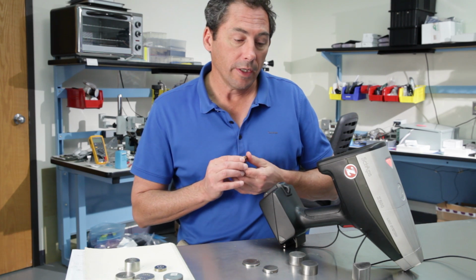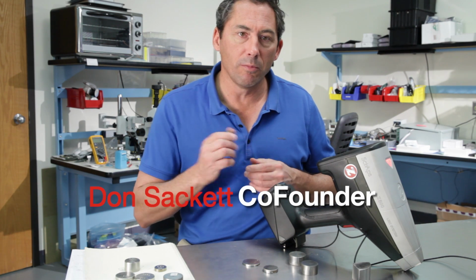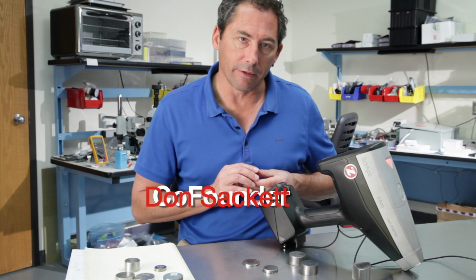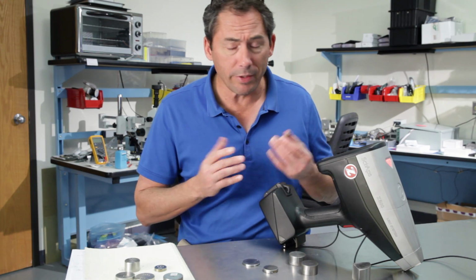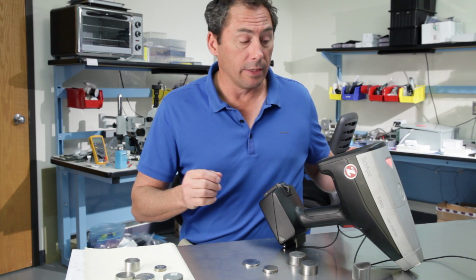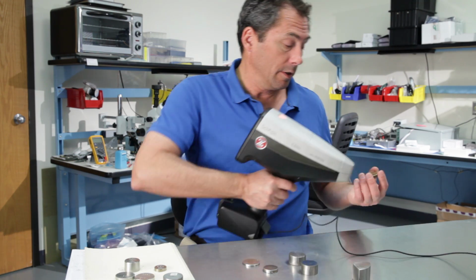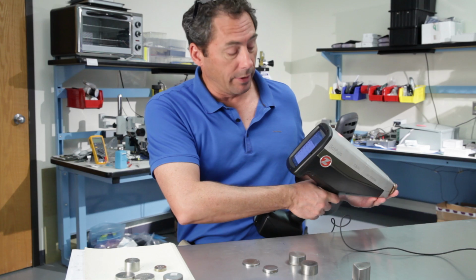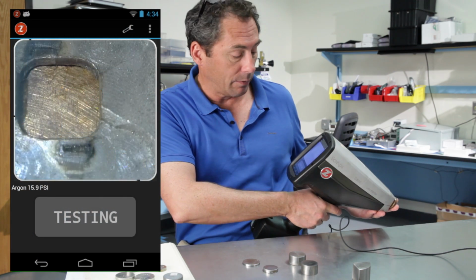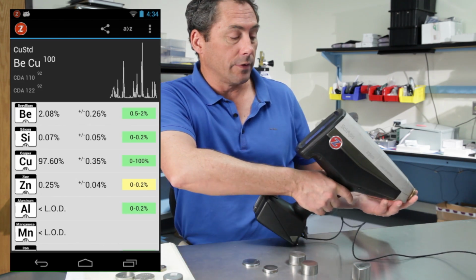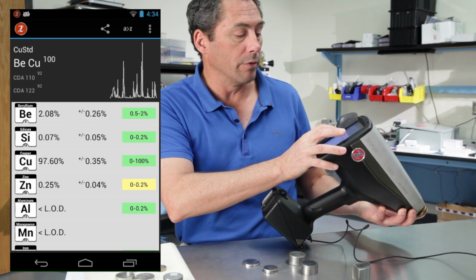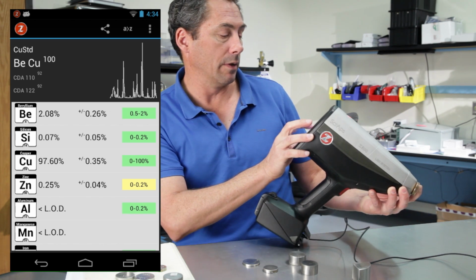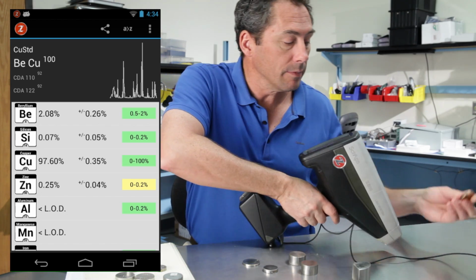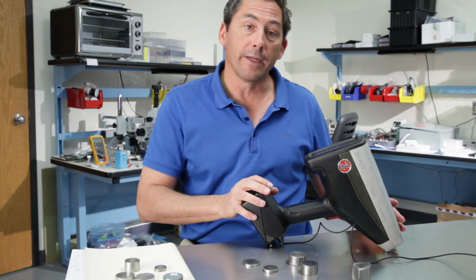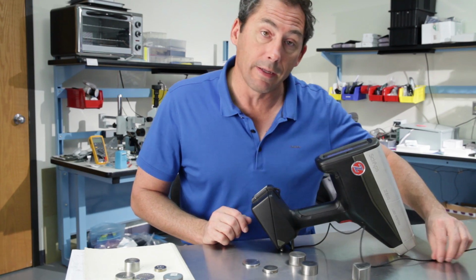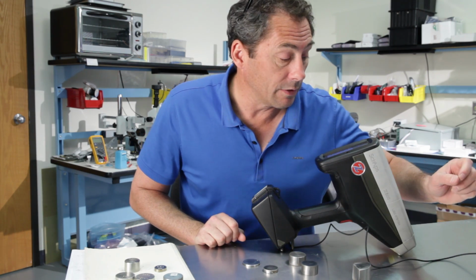One I like to show is a beryllium copper, because we're seeing more and more beryllium copper in these recycling facilities, and with X-ray you can't measure beryllium, so it's very hard to find that. So as an example of how quick and easy LIBS can be, there's a common beryllium copper. We'll shoot it, a couple of seconds, see it comes up, and there's your beryllium reading around 2%, which for this alloy is pretty typical. So that's a real benefit right there. You can measure an element that previously was not able to be measured with your other handheld device.